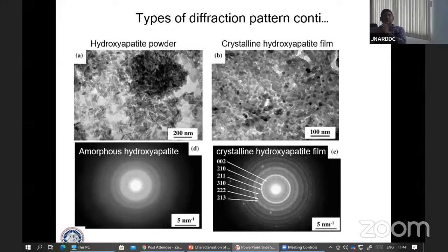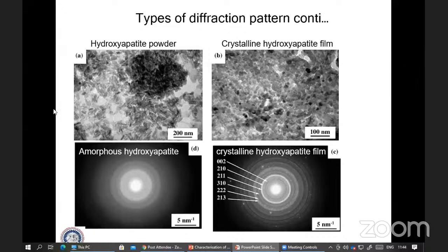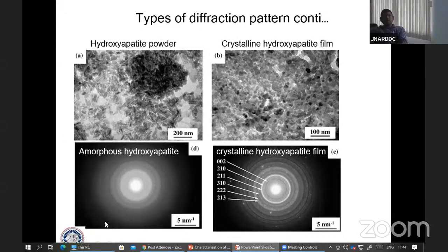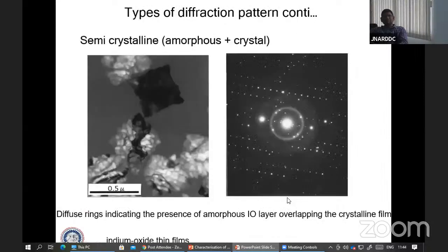Suppose you have hydroxyapatite which is amorphous in nature, that means you have a diffused ring pattern here. And suppose you have crystalline hydroxyapatite. Hydroxyapatite is of two types: one amorphous, and one powder with crystalline nature. So you will have spots with the diffused ring. So this is a spotty ring pattern. So you have a semi-crystal here. Suppose you see an indium oxide layer, you have a diffused ring with some spots, amorphous plus crystal.